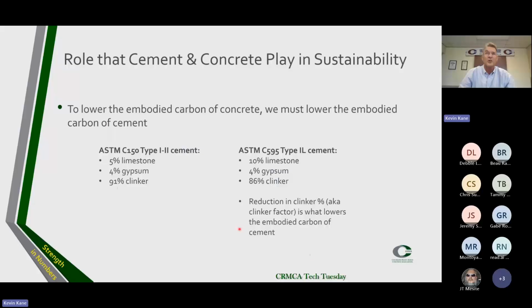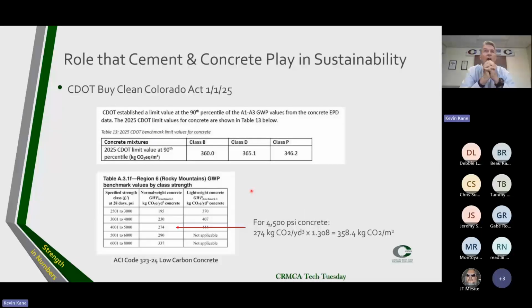So it's this reduction in clinker percentage, also known as the clinker factor, that lowers the embodied carbon of cement. That's the only lever we have to pull right now on the cement side. So Colorado passed the Buy Clean Colorado Act, effective January 1st of 2025, and they set benchmark limits on global warming potential of our concrete mixtures. For everyday Class D concrete, which is the bulk of our CDOT work, the global warming potential limit is 365.1 kilograms of CO2 per cubic meter.